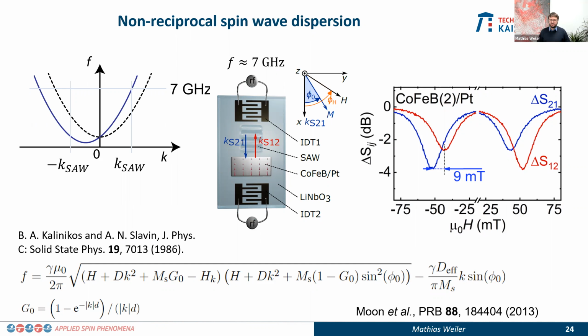And indeed it does. So if you look at the transmission data over here, you can see now there's a non-reciprocity not only in amplitude between the red and the blue curve over here, but also in resonance field, right? And that's because we now have a non-reciprocal spin wave dispersion. So to obtain the same frequency, we have to modify the external magnetic field for counter-propagating spin waves. Okay? And this non-reciprocity due to the Dzyaloshinskii-Moriya interaction, well, this form of this expression here, that comes from this work, this theory work shown here.